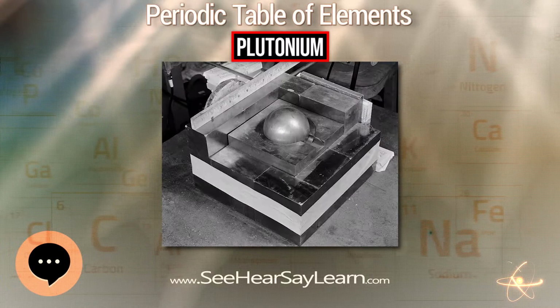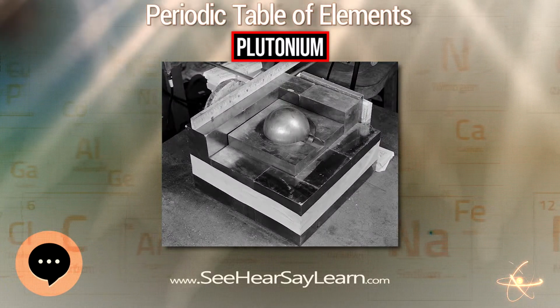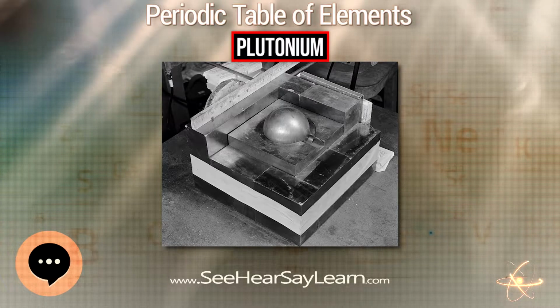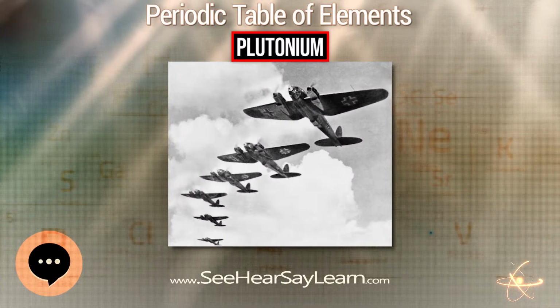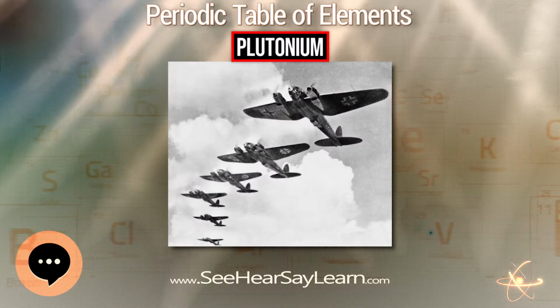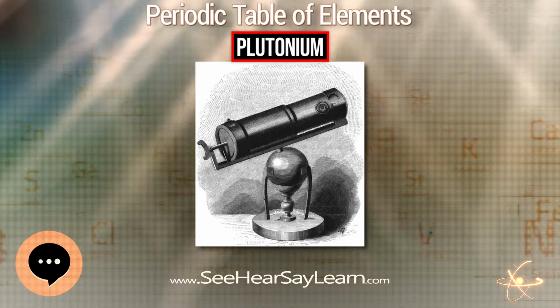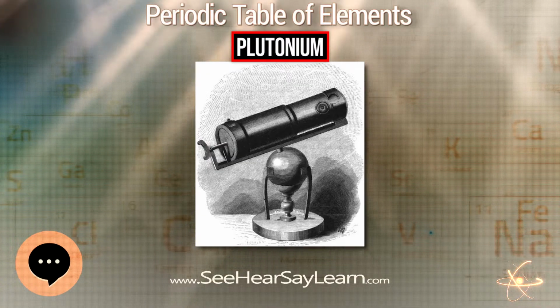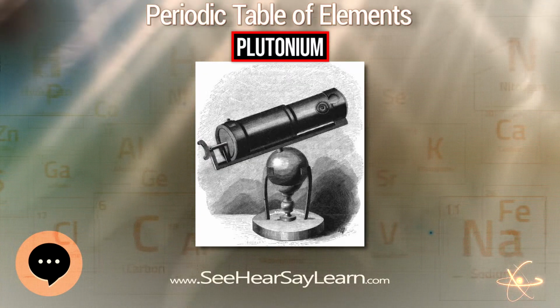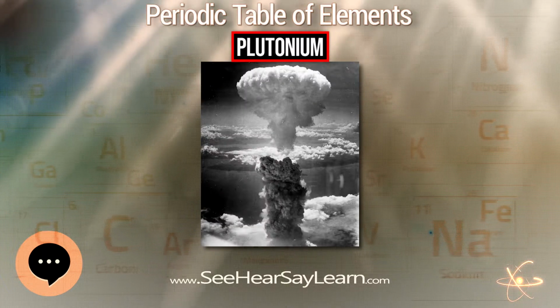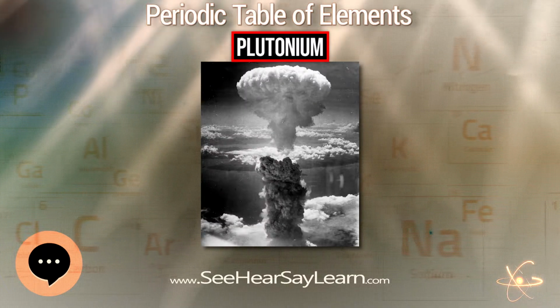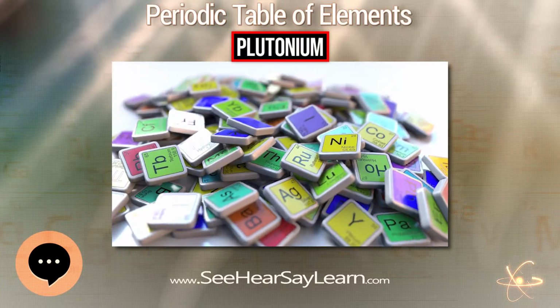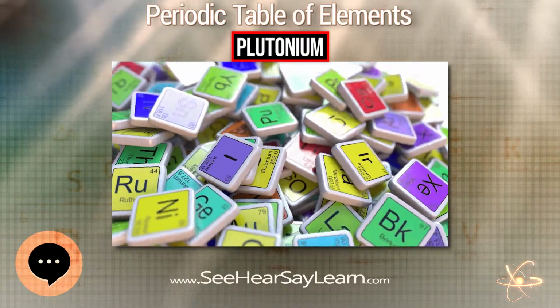High amounts of hafnium, holmium, and thallium also allow some retention of the delta phase at room temperature. Neptunium is the only element that can stabilize the alpha phase at higher temperatures. Plutonium alloys can be produced by adding a metal to molten plutonium. If the alloying metal is sufficiently reductive, plutonium can be added in the form of oxides or halides.